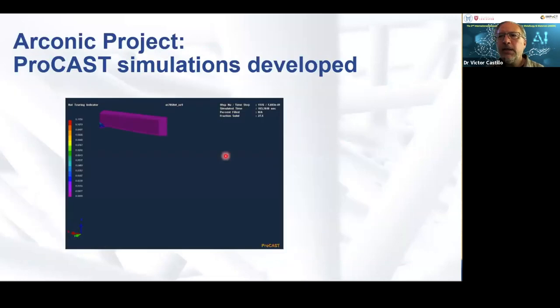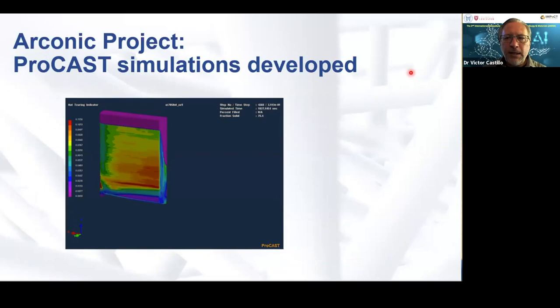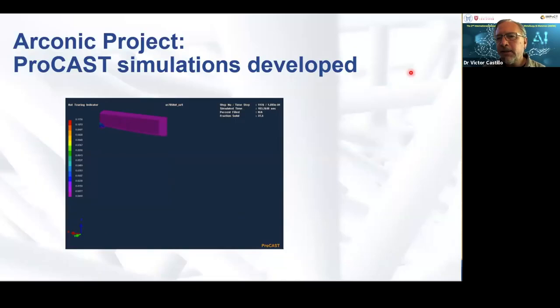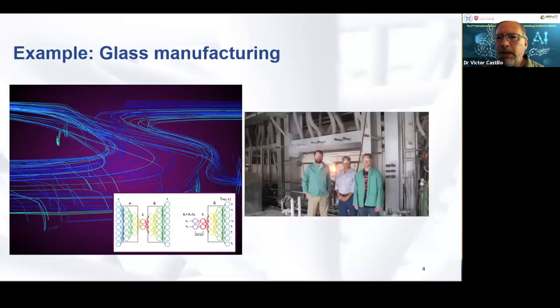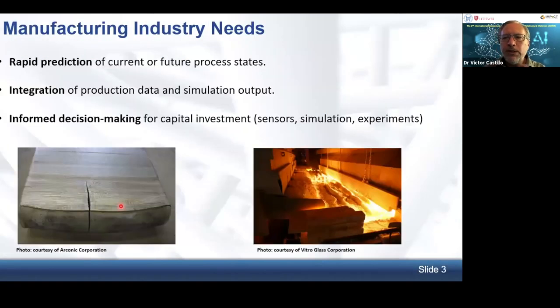and I'll show the output of the simulation. This movie shows the actual simulations that we ran in a commercial software called ProCAST. What we're showing is, over time, the ingot is forming. There's a solidification, and when it solidifies, there's some residual stress baked into the ingot. Maybe I should go back to show you the beginning here. Yeah, with the residual stress, once the ingot solidifies, you can get these cracks forming.